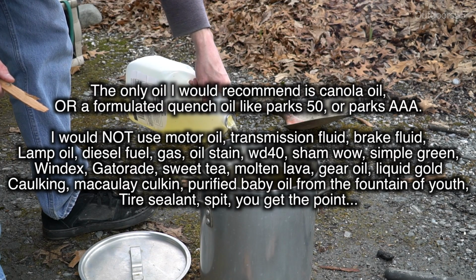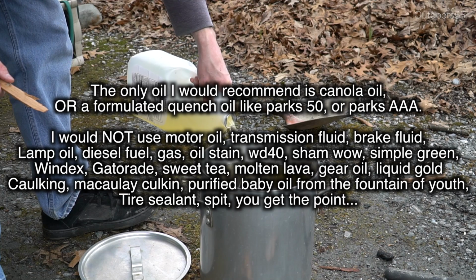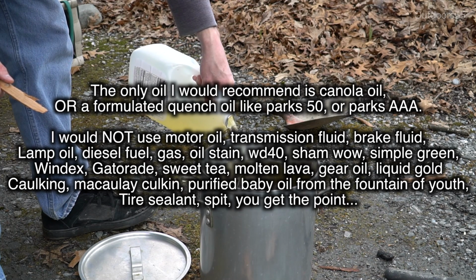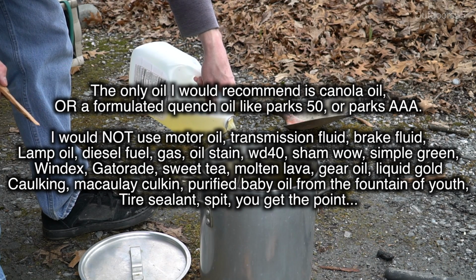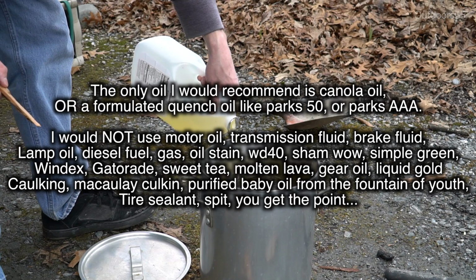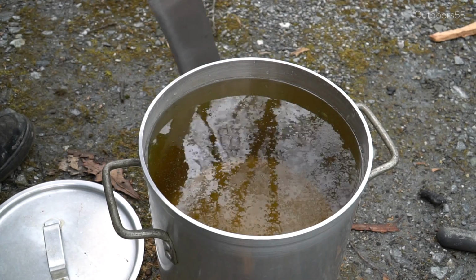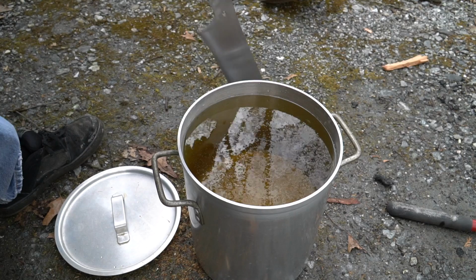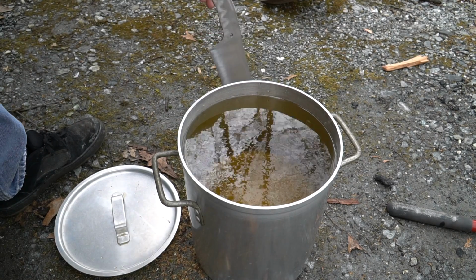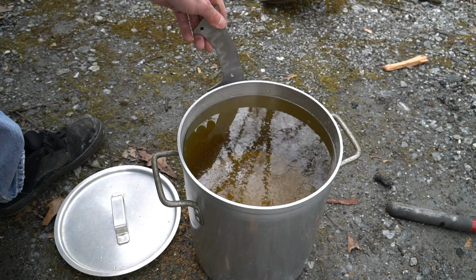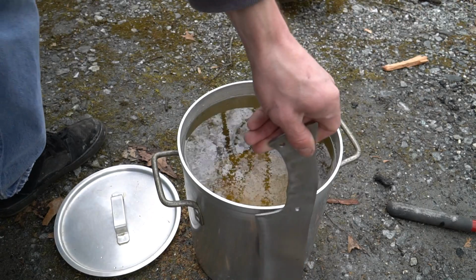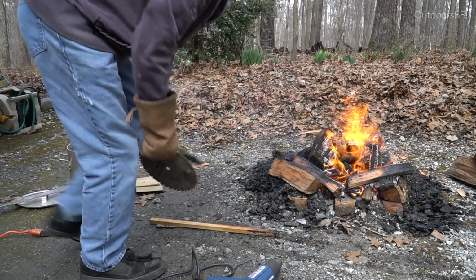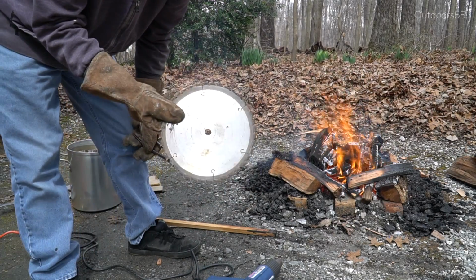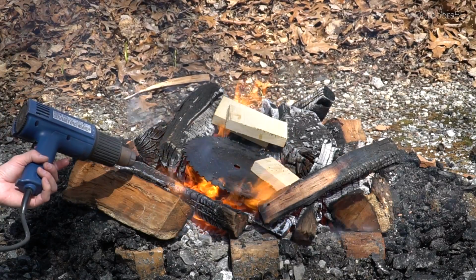You can use water if you absolutely must. I would not use cold water. I would use water heated to around 150 degrees. This oil will also be heated to around 120 degrees, 150 degrees. But if you do use water, know that you are greatly increasing the chances of cracking when you go to quench this. So the best way that you can actually preheat your oil is to take a piece of scrap steel. I'm just gonna use this old saw blade.